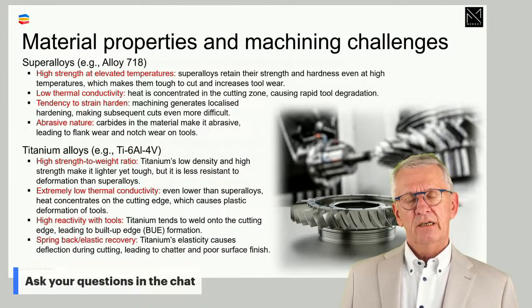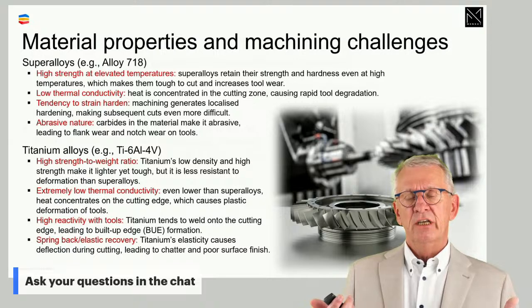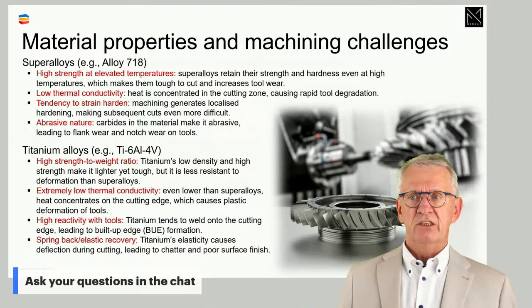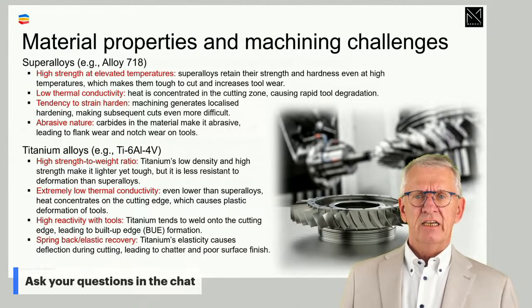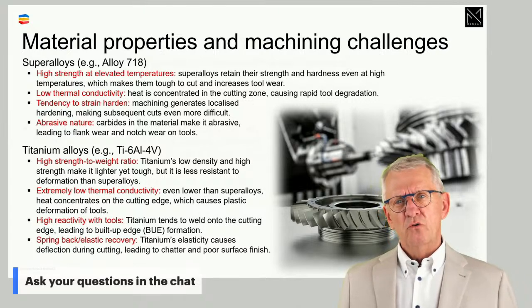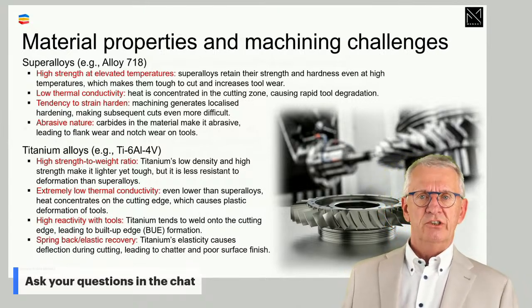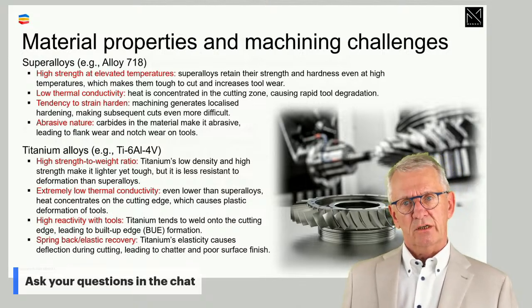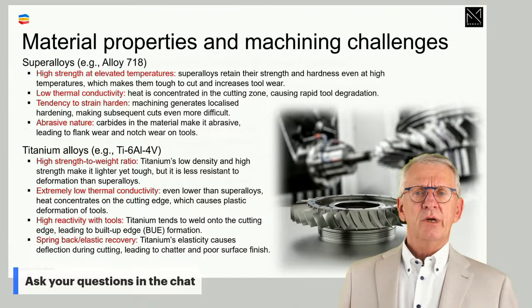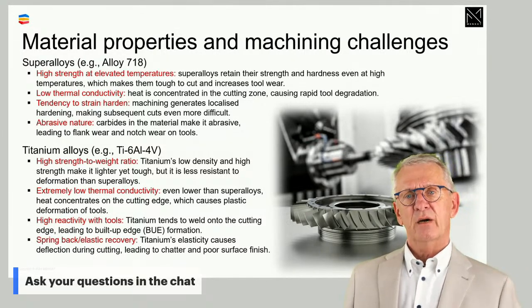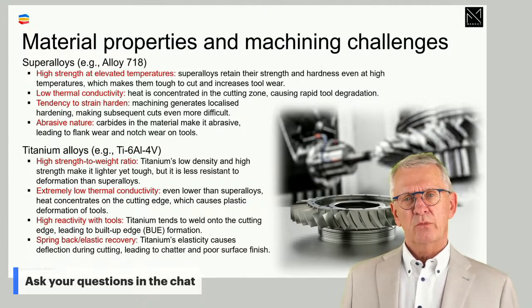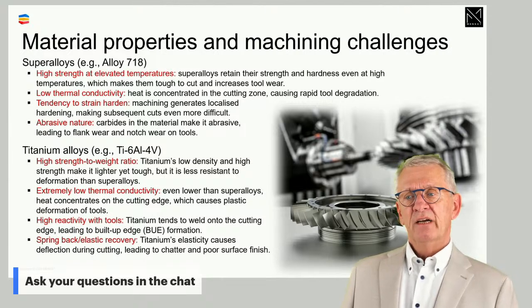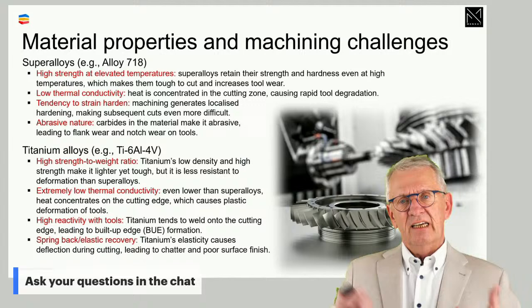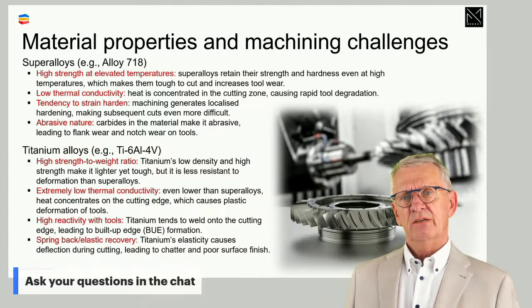Superalloys have low thermal conductivity. Titanium has an even lower thermal conductivity. So all the things about heat control, heat generation, heat evacuation, it's important in superalloys, but it's even more important in titanium alloys. Superalloys have a high tendency for strain hardening. Titanium alloys, not so much. That's important. However, titanium alloys show a tendency to chemically react with cutting materials. So here we see differences. Superalloys are abrasive. The strain-hardened spots, the precipitation-hardened spots are creating abrasive effects, where we don't find that so much in titanium alloy, but titanium alloys have an elastic recovery type of thing. They bend easily, and yeah, we have to be aware of that.